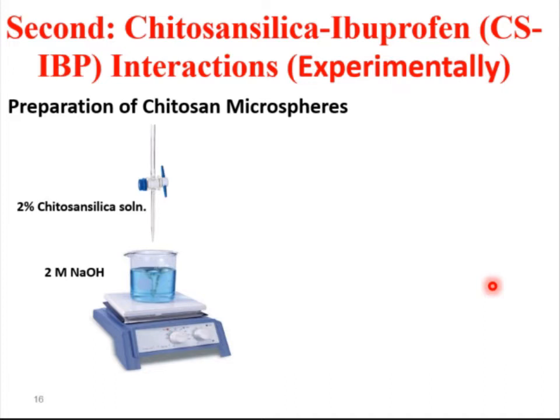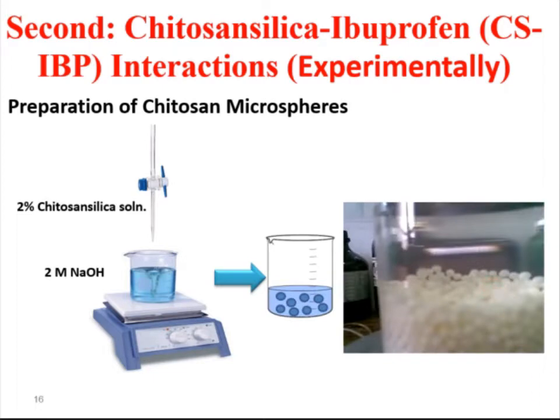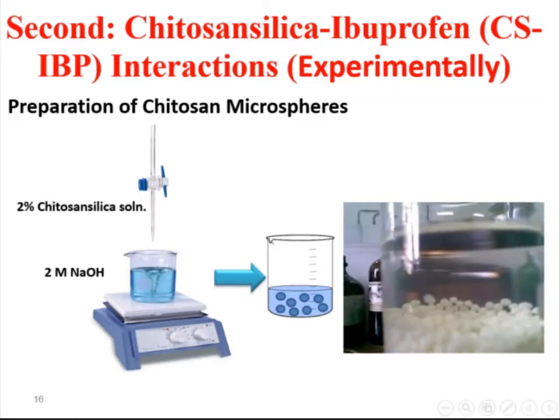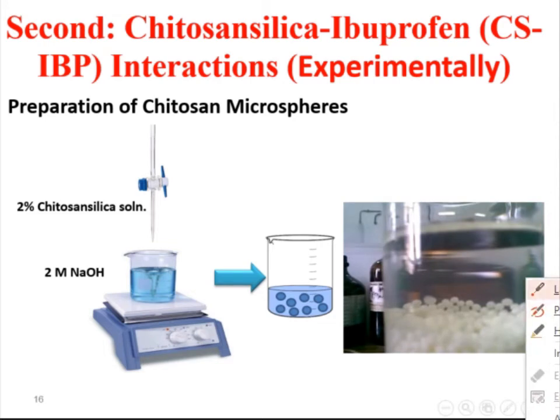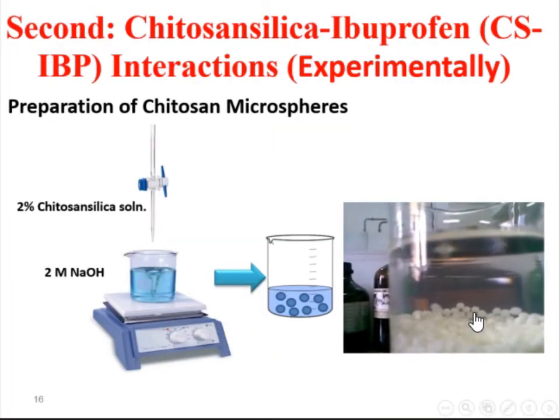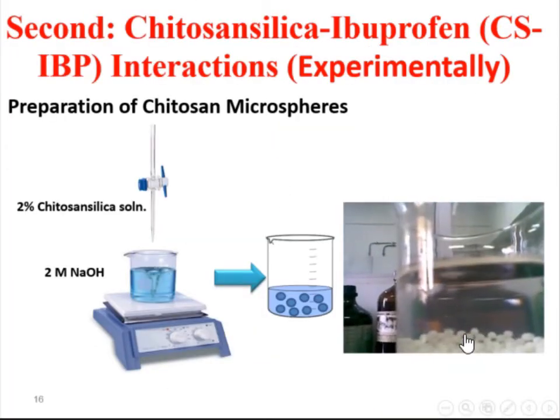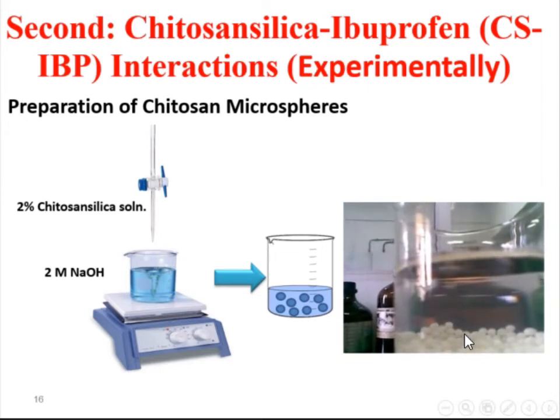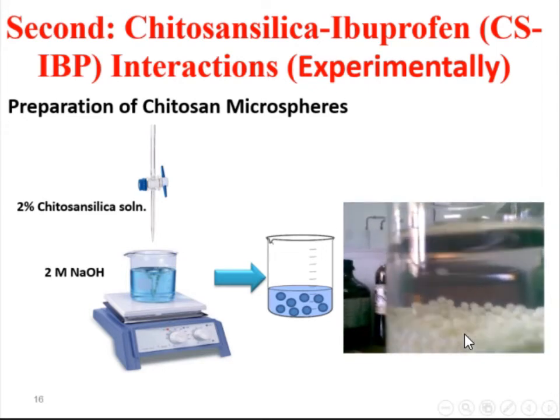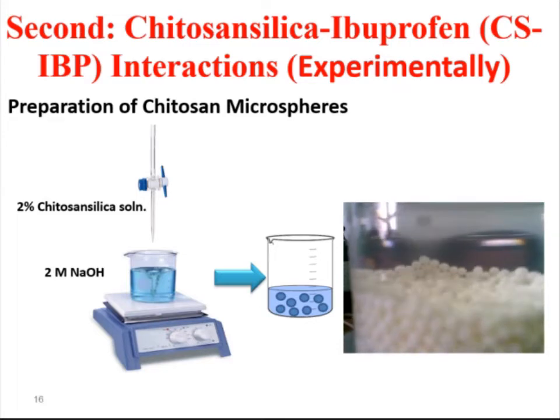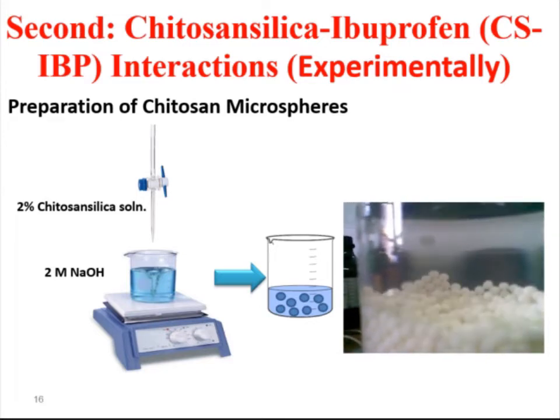Then, chitosan silica ibuprofen interactions through experimental approach, preparing chitosan silica microspheres through dropping chitosan silica solution into its crosslinker solution of sodium hydroxide, forming microspheres. And this is our video of the preparation process. We can notice that drops of chitosan silica solution are freely dropped into crosslinker solution.